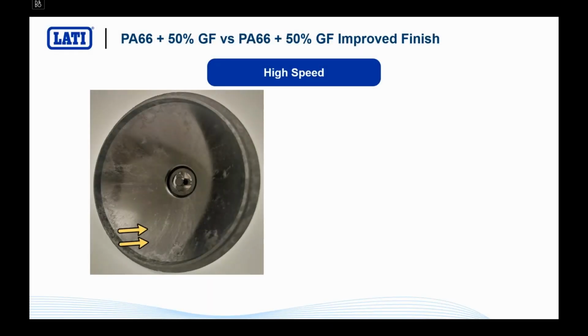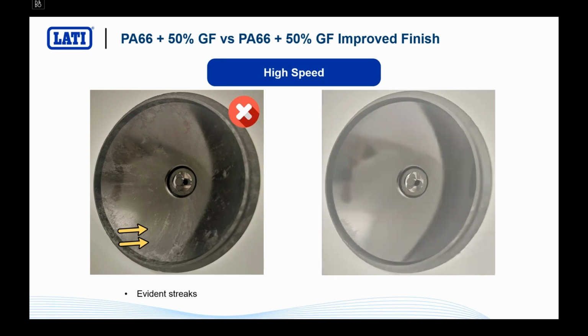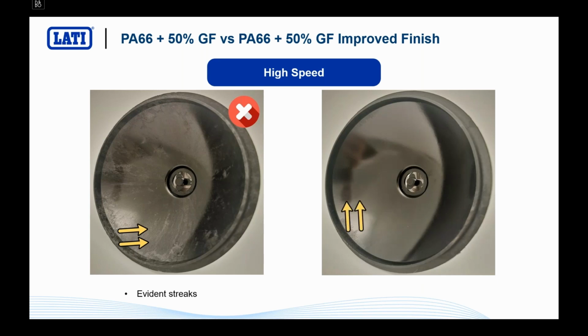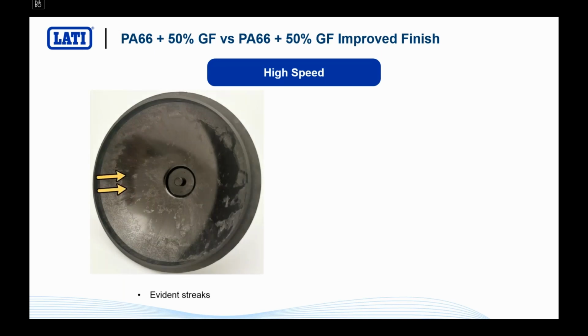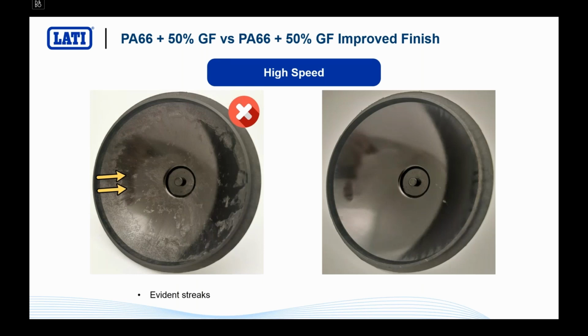What happens with high speed? You see it here. The standard grade is always bad looking, always poor looking. There is no way to improve this kind of typical formula, but the improved finish formula, which is tuned in the matrix part, is absolutely glossy and very good looking. Not only with the three gates, but also with the fan gate. You see it here. Also in this case, you have a much better performance from a surface finish point of view, even with the fan gate. So the conclusion of this specific part of our design of experiment is that with some formulas, there is no way to improve it just by tuning the speed. You have to tune the formula of the material as well, as in this case.